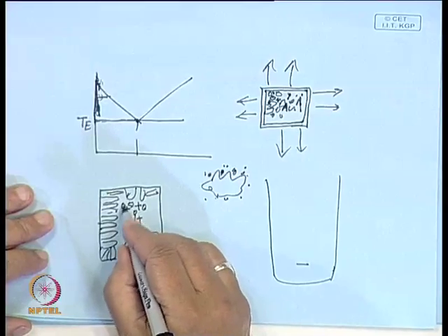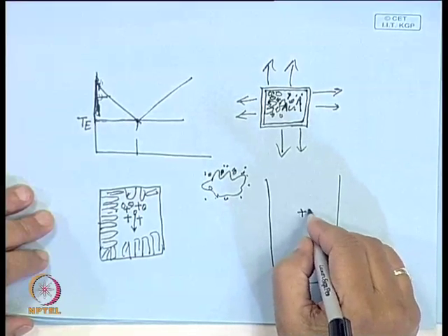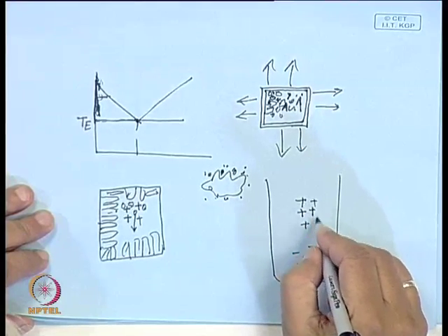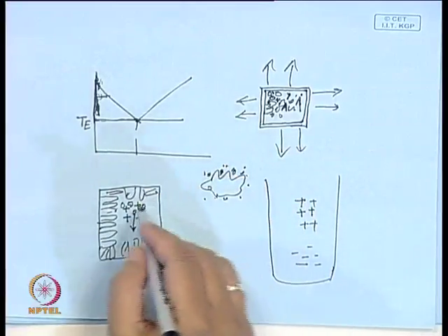The first solid that precipitates out is purer. So you get negative segregation here and positive segregation in these parts, and this segregation you will always get in alloys. One way you can control it is by controlling the processing, the nature and the extent of segregation. Segregation which is macroscopic will be very difficult to remove by any subsequent heat treatment. Segregation which is very large, which you can see by the naked eye, will be very difficult to remove.